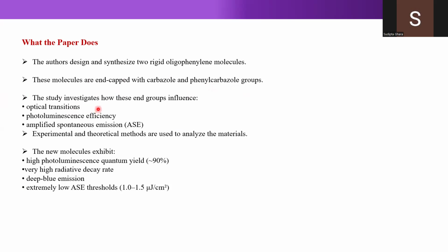And they did different types of photophysical studies, like the optical transition, photoluminescence efficiency, ASE measurement, and they did theoretical studies also. The new molecules exhibit a luminescence quantum yield of nearly 90%, which is very attractive, and very high radiative decay was also observed.